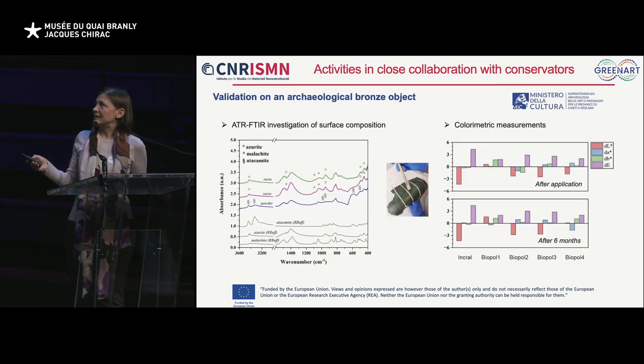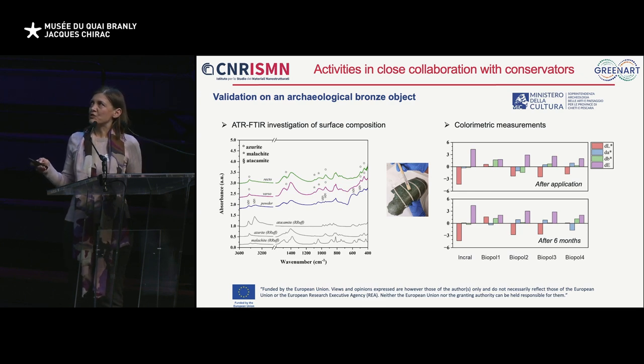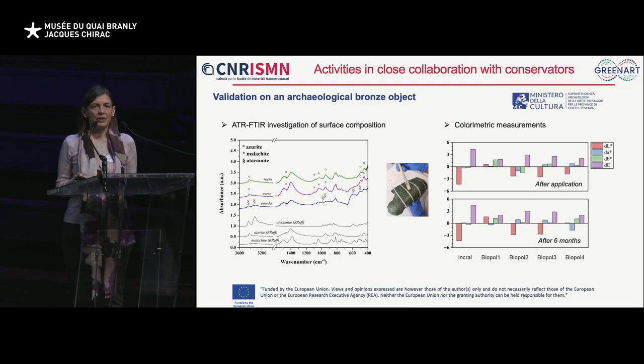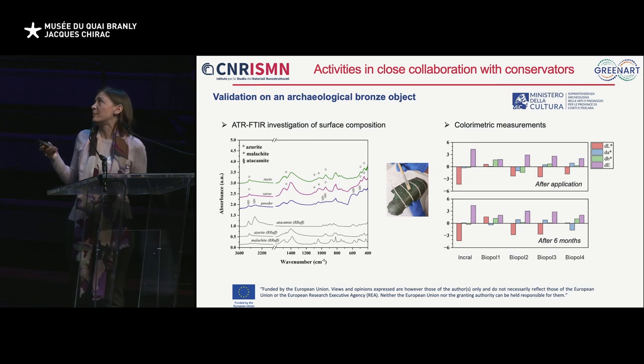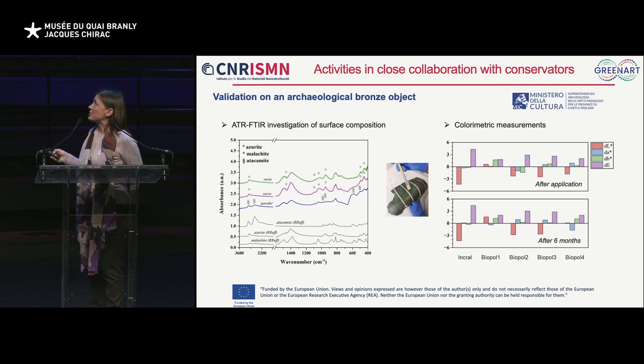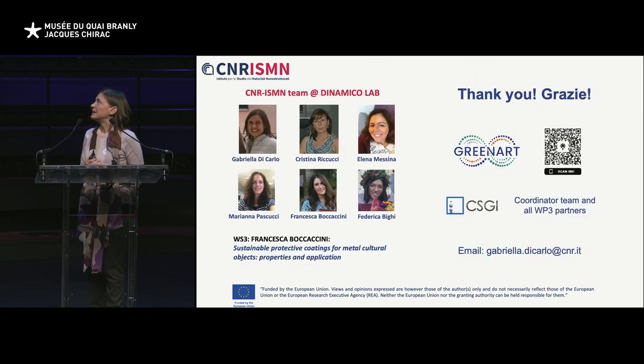So in this slide, you can see the results of the characterization of the object before the application of the products, and we can see the common degradation products typically observed on archaeological bronzes. And we also performed the colorimetric measurement after the application and after 6 months. The colorimetric parameters are quite stable, but we can observe, for example, that the delta E is slightly lower, and in particular the delta L, which is related to the luminosity of the surface, is slightly lower with the new formulation. And so finally, I want just to thank all my group which worked on this project.